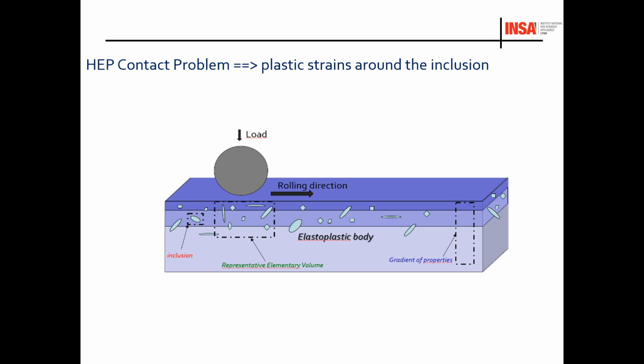And then we have been able to study fatigue of materials like that, using different types of inclusions of different geometries, different sizes, different materials, and it's possible using artificial intelligence, for example, to perform many simulations and to try to get some trends. It is interesting to see that there is a combination of effects: small versus large inclusions, inclusions that are close or not to the surface, and also the stiffness of the inclusions.